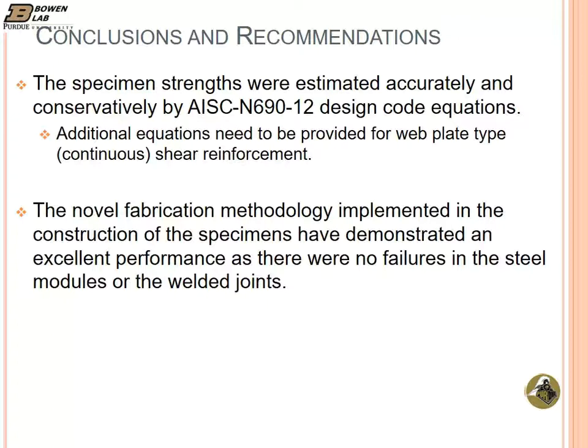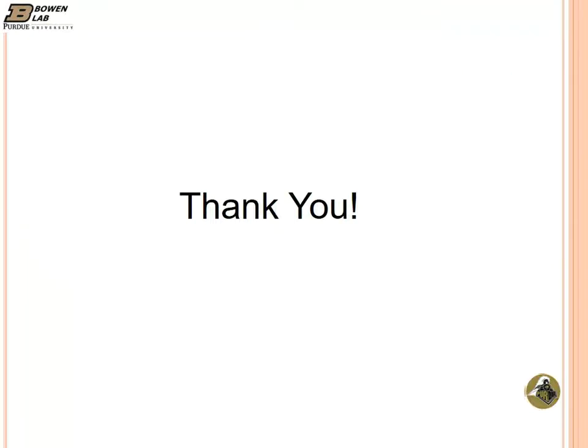Both specimens were conservatively estimated using the code. And as you saw in the pictures, the failure was always in concrete. We didn't have any failure in the steel. That also shows us the fabrication quality was excellent, and we didn't have any failures in the welds or any joint regions. All the failure was governed by the concrete, so the steel fabrication held up very well. That's the end of my talk, and thanks for your attention.